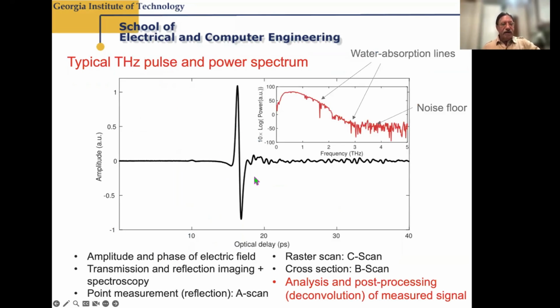The black trace here is a typical terahertz signal, roughly a single electromagnetic cycle, about 3 or 4 picoseconds long. And all the signal that follows is the ringing resonances in atmospheric water vapor. The inset here shows the power spectrum. So we have signal from about 50 or 60 gigahertz up to about 3 terahertz, and then this is just noise. But here in this power spectrum, we see features associated with atmospheric water vapor absorption. Now, we can get rid of that in two ways. We can remove the water vapor by flowing dry nitrogen over our sample during the experiment. Or since this is reproducible, we can get rid of it with denoising, signal processing tricks.